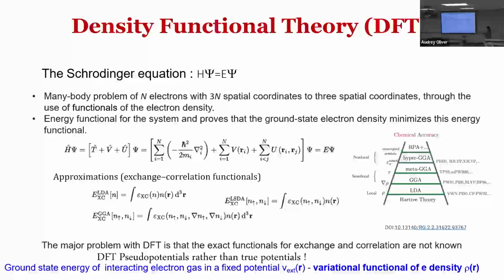So the Hamiltonian has a kinetic term and a potential term, right? And then what we do is use some approximation for the exchange correlation part. For example, in LDA, what we consider is that the electron density is constant at different locations. And then in GGA, instead of just having that electron density fixed, we have a gradient so that we get a distribution of electron density in the system. These are what we call the standard density functionals. We use those, but if you see here, one of the basic theories is Hartree theory, and then LDA, GGA, and there are many functionals. As you go up, it's more accurate, but it's time consuming, an expensive calculation.